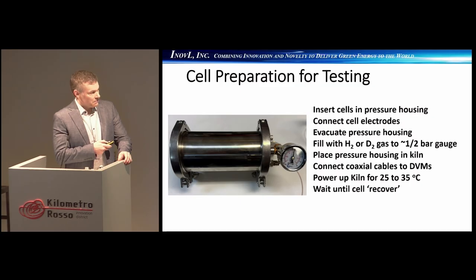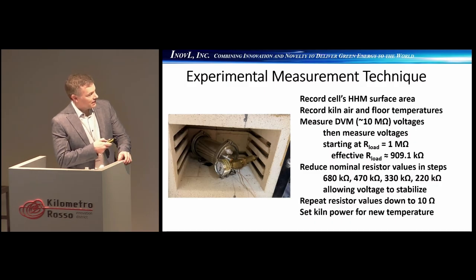And if you go higher in temperature and try and push the mobility of the ions higher to try and get more flux of the hydrogen deuterium in, it can stunt the cell from there on. So you do need to kind of be careful in how you bring it back up. And here's kind of an example of this. Our cell is in the kiln here.